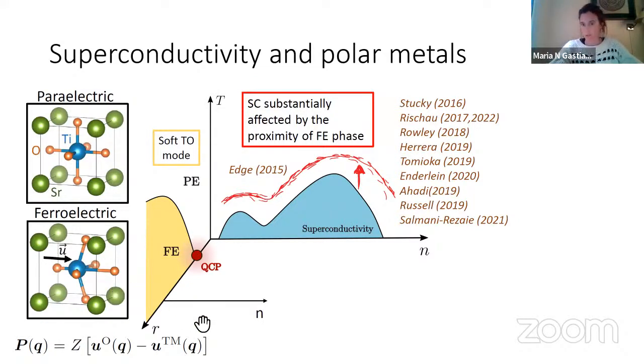trying to see whether this mode or these ferroelectric fluctuations are important? In the last few years, a lot of different groups, with different experiments, have shown an intimate connection between how close you are to this ferroelectric phase and what Tc does in the superconducting phase. For example, there have been reports that if you move the system closer into the ferroelectric phase, you can get enhancements up to a factor of 3, and so on. So now the idea is, could this coupling between the electrons and the ferroelectric fluctuations be the most important mechanism for superconductivity,